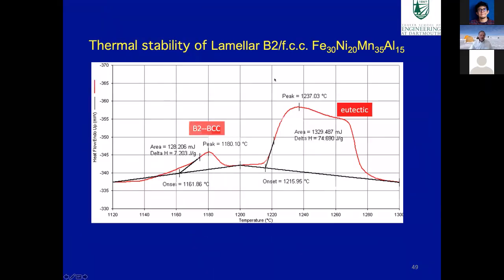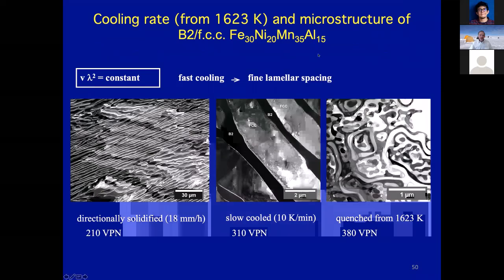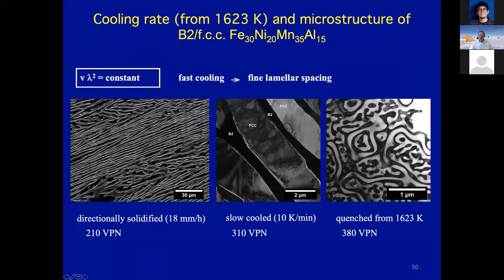We did some calorimetry on this material, and we see a couple of peaks. We see this peak here at about 1180 centigrade, and this we think corresponds to the B2 to BCC transformation. And then we get a peak around 1237, which is melting the material. We've actually processed this material in several different ways. So we directionally solidified it, we slow cooled it after melting, and we quenched it after melting. And you can see there's quite a change in the microstructure. If you look at the scales here, they are quite different. This directionally solidified has quite a coarse scale, and over here we've actually got quite a fine scale and a very unusual microstructure. And as you might expect, as you go to a finer microstructure, the hardness increases.